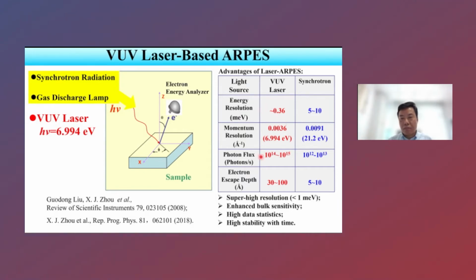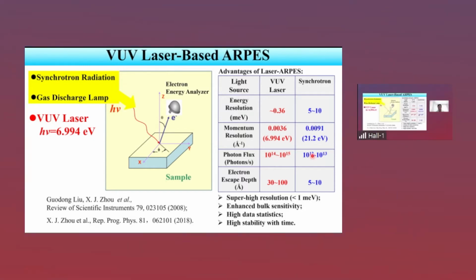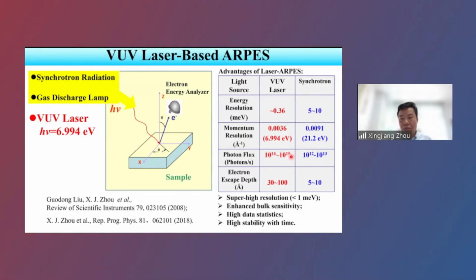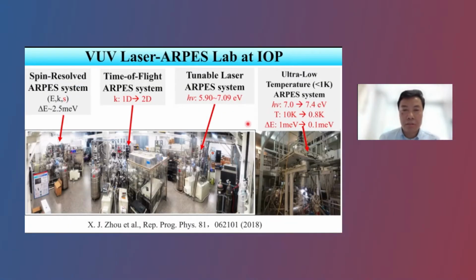Also, the photon flux is very high. Usually, it's about 2 orders of magnitude higher than synchrotron. That means you have high data quality and also high efficiency, and also some other advantages. I think laser ARPES is a really powerful technique to study high-temperature superconductors. And in the last about 16 years, our group has been developing laser ARPES.